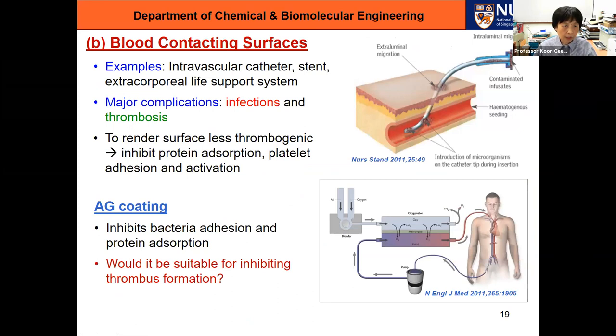Now let me move on to blood contacting surfaces. Examples of blood contacting surfaces would be intravascular stents, catheters, extracorporeal life support systems. And again, infections is one of the main problems. But another problem is thrombosis, the forming of blood clots. So to render this catheter surface less thrombogenic, we will need to inhibit protein adsorption, platelet adhesion, platelet activation. So since we already have the agarose coating, we ask whether it is possible to use this for blood contacting devices, because we know that the agarose coating can inhibit bacteria adhesion, it can inhibit protein adsorption. Would it be suitable then for inhibiting thrombus formation?